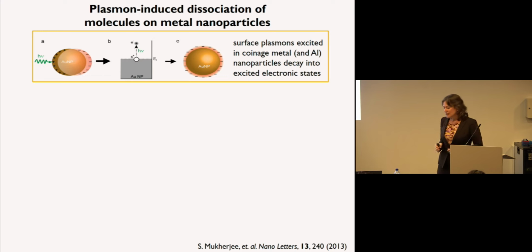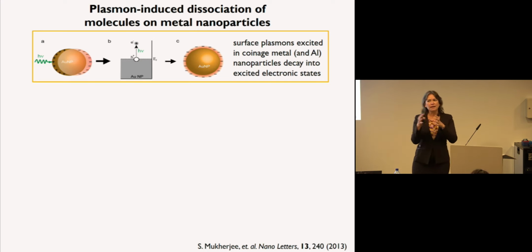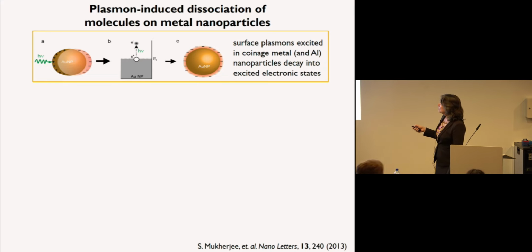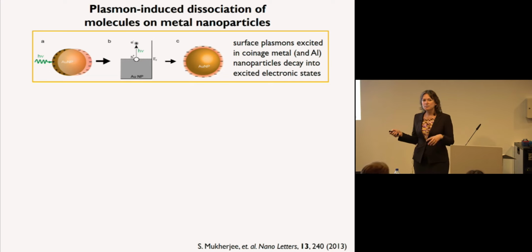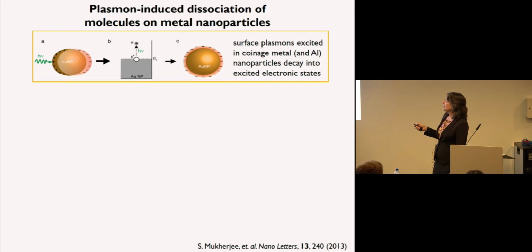It's not just gold that does this. Any of the coinage metals, so copper, silver and gold, as well as aluminum, can absorb visible light, tunable depending on the size of the nanoparticle, and create so-called plasmons, which are collective excitations of the valence electrons that live on the surface of the particle. What can happen, as this cartoon shows, is they can decay through various mechanisms. One mechanism is to create electron-hole pairs, an excited electronic state that is in fact localized. And those electrons can then be accessed to do chemistry, so it is thought.